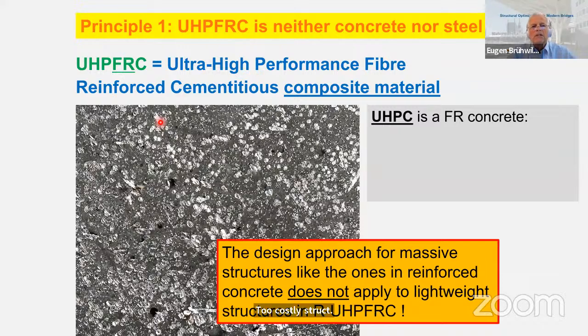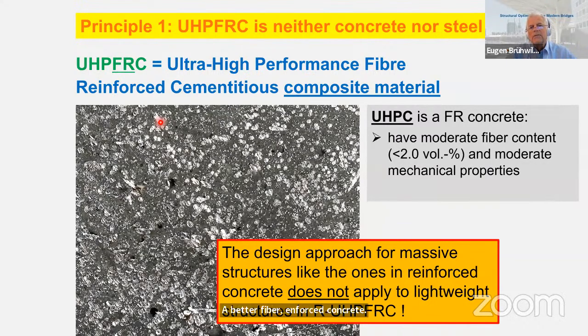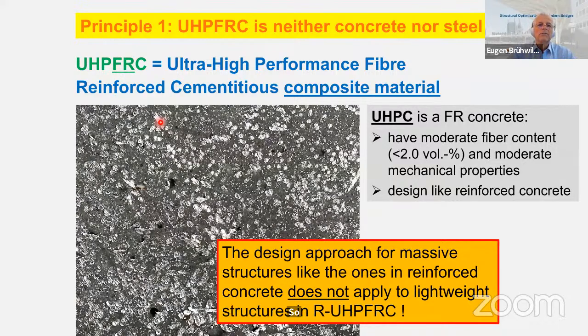Okay? Such materials are under the name of UHPC, which is in many cases just a better fiber-reinforced concrete. They have moderate fiber contents, smaller than 2% in volume, typically, and as a consequence, rather moderate mechanical properties. And these materials are, as I mentioned already, designed like reinforced concrete. This is not the way to go here. So what I'm introducing here today is UHPFRC and the very specific design principles that belong to this material.